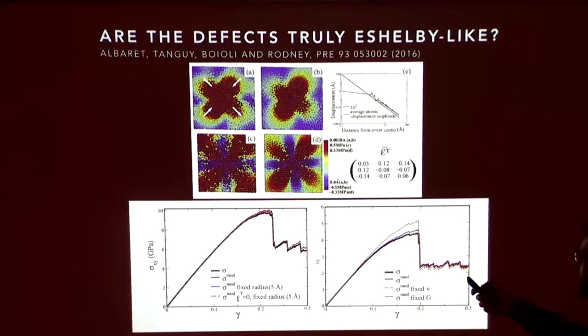They use the fact that, according to Eshelby, there should be a particular signature of this elastic or plastic event, because it's surrounded by an elastic field, embedded in an elastic medium. This shows the displacement field expected around an Eshelby inclusion as seen in their atomistic simulations, and also the stress field that develops around one of these inclusions.